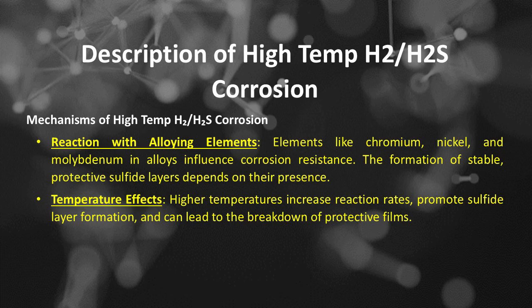The third is reaction with alloying elements. Elements like chromium, nickel, and molybdenum in alloys influence corrosion resistance. The formation of stable, protective sulfide layers depends on their presence. And the fourth is temperature effects. Higher temperatures increase reaction rates, promote sulfide layer formation, and can lead to the breakdown of protective films.